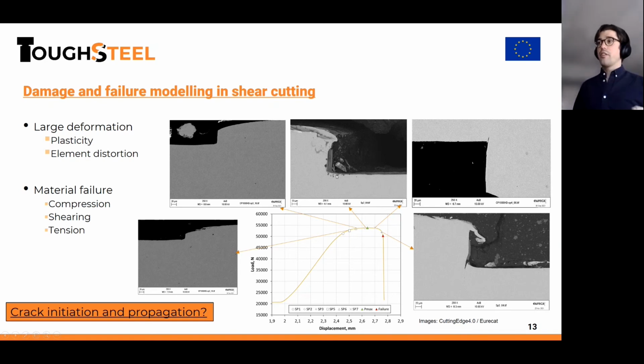Then we have the material failure. So when the rollover is finished, we have a failure in mixed compressive shear stress. Then we have pure shear material failure. And then in the end of the shearing process, we have a kind of mixed tensile shear failure. And also looking back on our previous results, this also seems possible to do with the GISSMO model, if you remember that we could model failure for a lot of different stress states in our tensile testing.